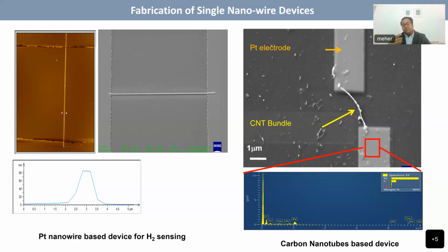So when we tried to purge the gas in the chamber, and when we tried to measure the change in resistance because of the gas, we could find that the change in signal is much less than the noise which we were getting. So the electronic system was not that sensitive. And the second problem was the surface area available for adsorption of hydrogen gas was not enough to give a clear change in the signal.